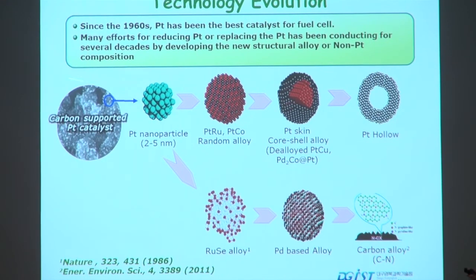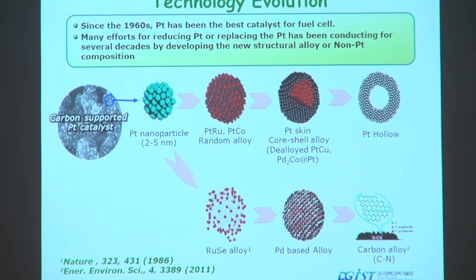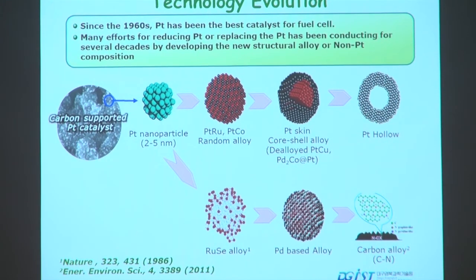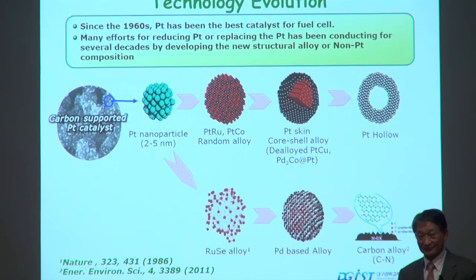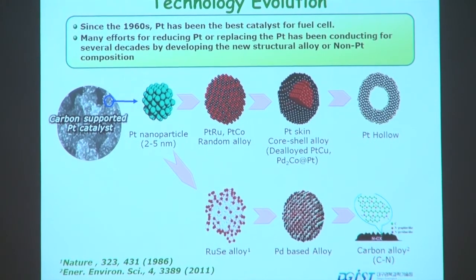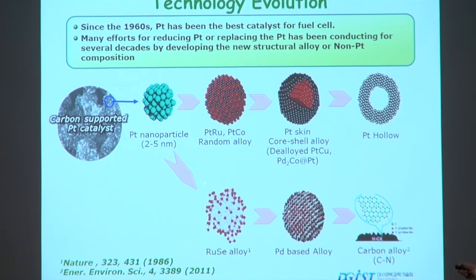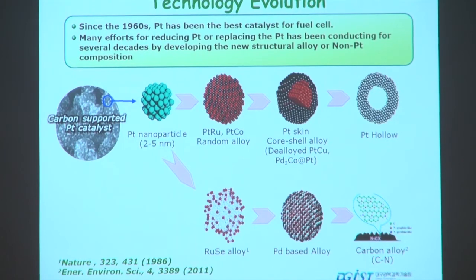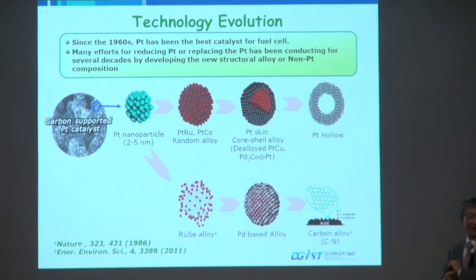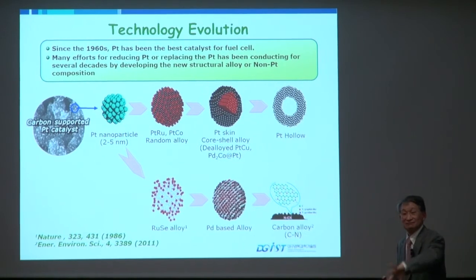Then people came up with the idea, how about removing this carbon? So neat catalyst. But it turned out that stability is not very good, activity is not very good. Then it moves to random alloys to reduce the amount of platinum. Then the activity turned out to be pretty good. But the problem is the transition metal is rather easily leached into the electrolyte. Then the activity decreased.